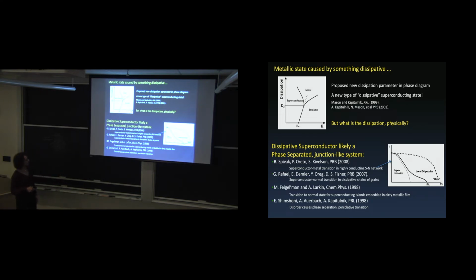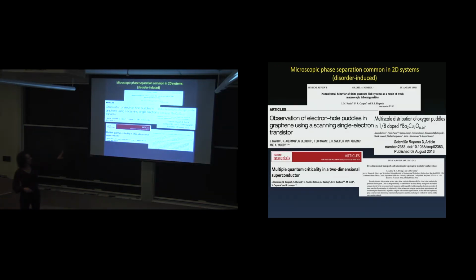So there are a lot of theories about having regions of superconductor and regions of normal metal in this system, which could lead to this kind of dissipative superconducting state. Now, these were theories that talked about phase separation in a superconductor, but I think this is even more general. It turns out that this sort of microscopic phase separation happens generally for low-dimensional systems. In general, if you have a 2D system and it interacts with anything, a substrate, a surface, the air, it leads to little regions that have different charges, different strain, some differences. And as you lower the temperature on a 2D system, which is fragile to perturbations, it will tend to break up into regions that have different properties.